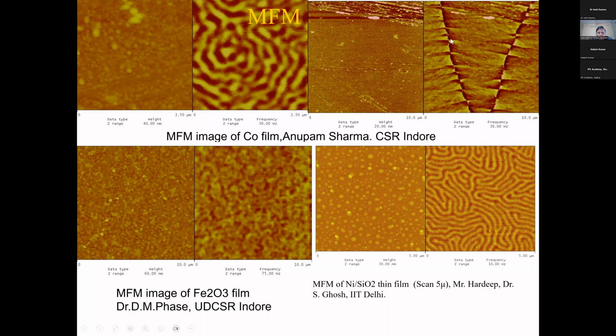People need to know a little bit about magnetism. And if you increase the thickness, this is about 20 to 30 nanometers, now about 300 nanometers, then you can see all the domains change. You will see percolating circular domains. The width of these ripples you can measure, and it goes inversely as a function of thickness, and this scaling is also available to you. That's what I said, first page, third page. See, it's only simple dots, small grains and grain boundaries. This is a nickel on silicon oxide film. There's nothing, only grain and grain boundary, nothing small, spherical particles. But the right side is the magnetism. The domain is very beautiful, a percolating domain.